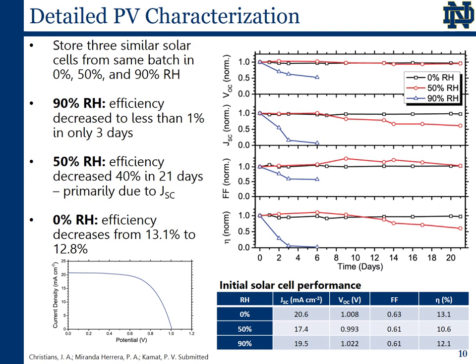Finally, in correlating these findings with photovoltaic performance measurements, we observe an almost total degradation of photovoltaic performance in only 3 days when the solar cell is stored at 90% relative humidity. As expected, the solar cell stored at 50% relative humidity degraded much more slowly, but still decreased in performance by 40% in only 3 weeks.